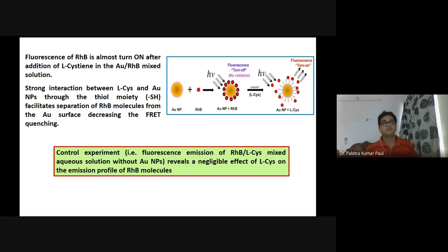Hussain. So this is the fluorescence of rhodamine B, and a strong interaction with L-Cysteine and Au nanoparticles through the thiol moieties facilitates separation of rhodamine B molecules from the Au surface, decreasing the FRET quenching. So the quenched, what I explained, that is, increasing the concentration, the quenching basically decreases. And we also checked the control. We have checked the control experiment.